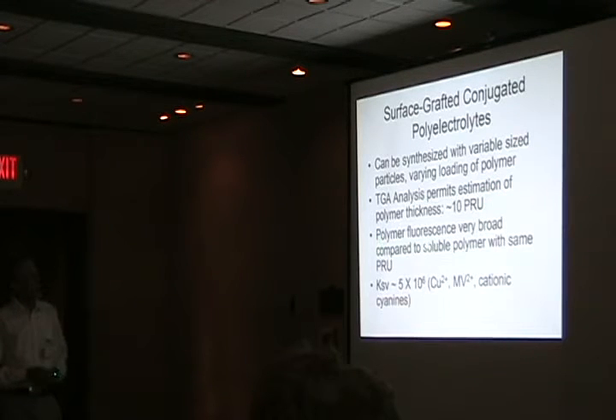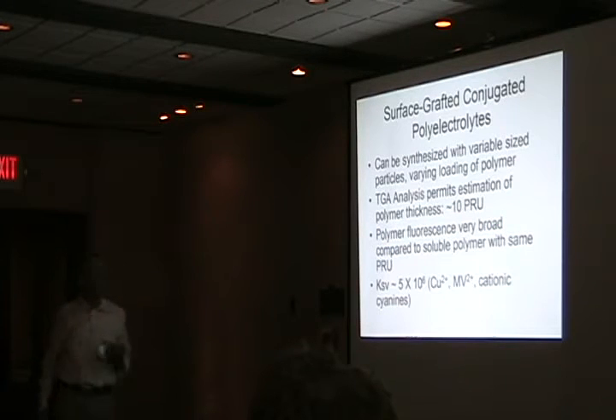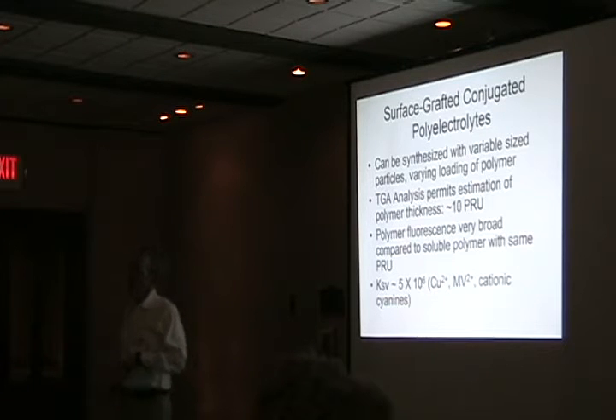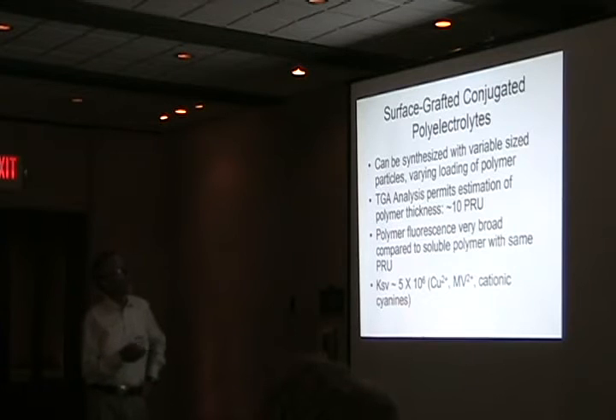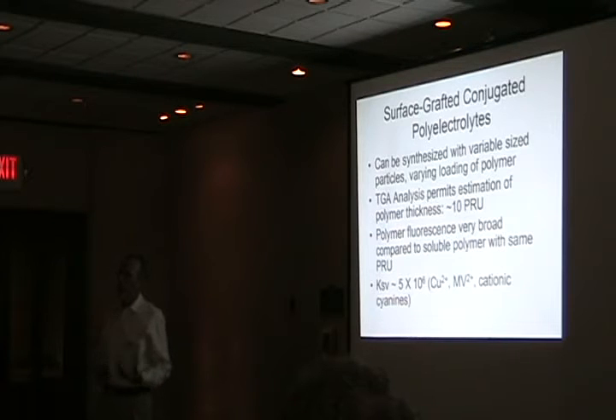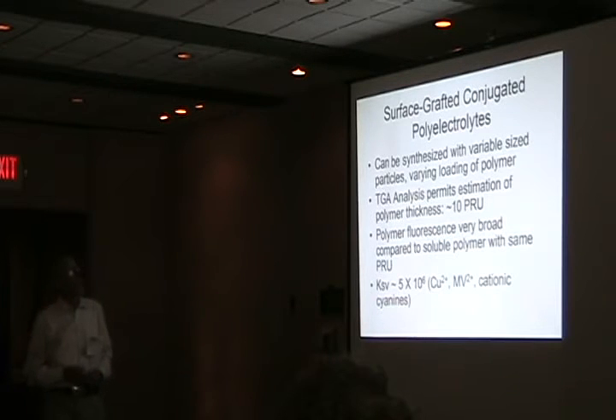So the polymer fluorescence and excitation are very different from the soluble polymer with the same number of polymer repeat units. The fluorescence excitation spectrum is blue shifted. The fluorescence of the surface grafted conjugated polyelectrolytes is actually shifted to the red. It's very broad and featureless. And the quantum efficiency is probably about half what that is for the parent polymer in solution. It's still maybe 20% or so, but it's definitely reduced.